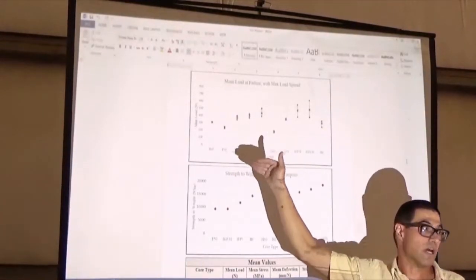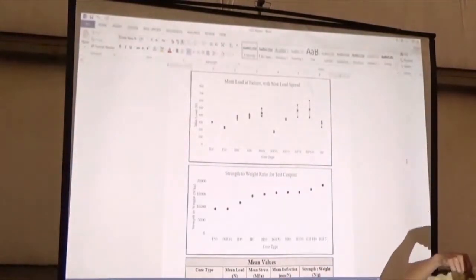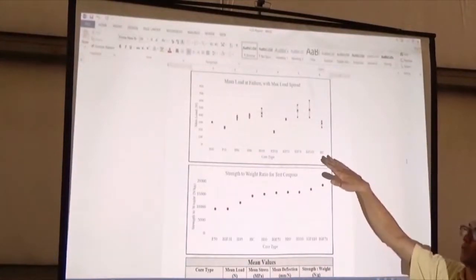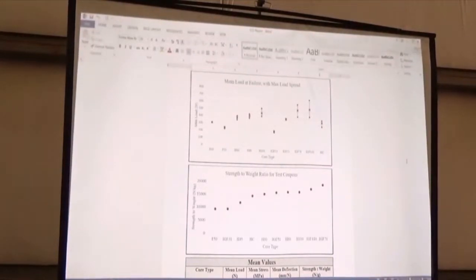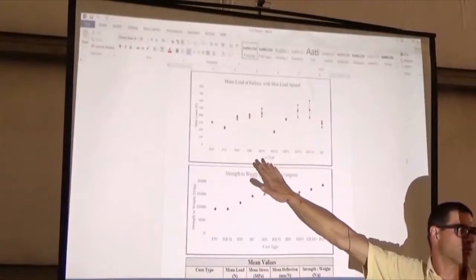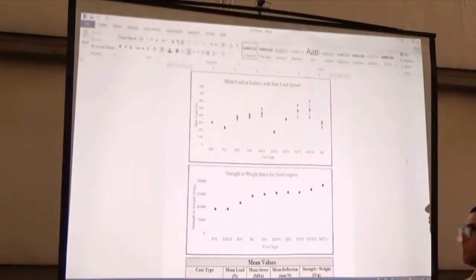So the Divinycell is a denser foam, but it doesn't perform as well as the Rohacell, because the Rohacell has better mechanical properties. The problem with the Rohacell is that because it's very frangible, any kind of impact, you have a delam. And so I would never use Rohacell on an external structure like a wing skin. It's great for internal structures like spars or ribs, something that's not going to suffer from delamination problems. But the Divinycell performs better for things that might be getting bumped around.